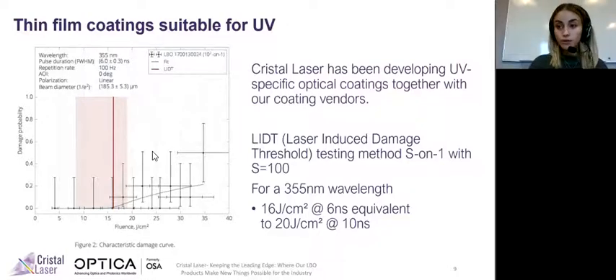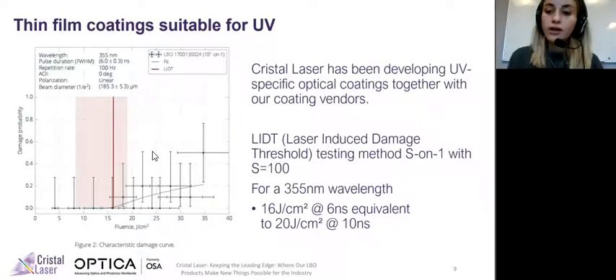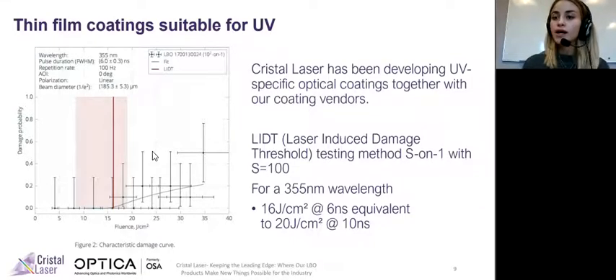So this is a really impressive and outstanding result because this is a very high LIDT, especially considering the wavelength. And this parameter is very important because high LIDT is what prevents a catastrophic failure of the crystal and hence of the whole laser system. Furthermore, beyond the LIDT, we also worked on a dedicated bench to better understand and study the mechanism of degradation of the crystal under UV light. So we developed a bench especially for this kind of application at Cristal Laser.